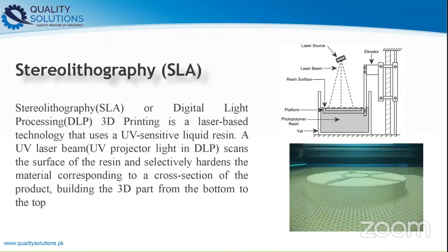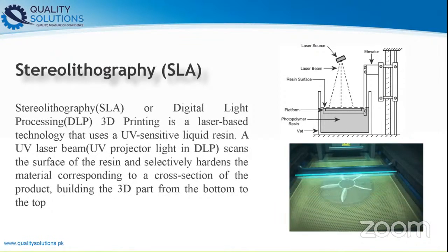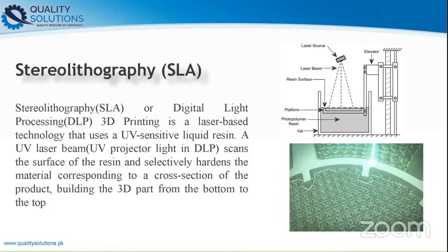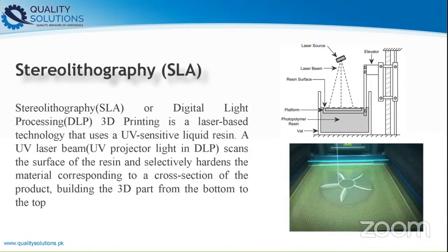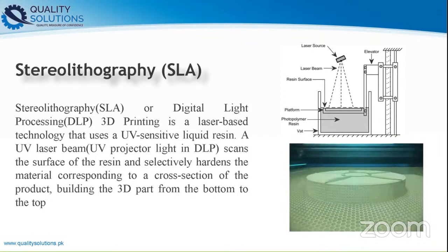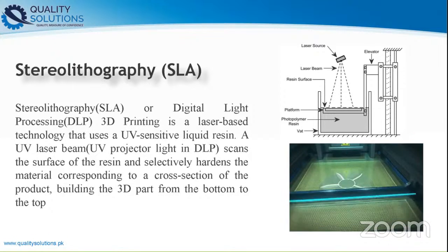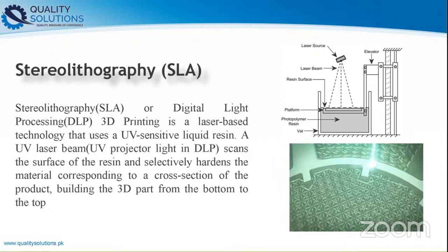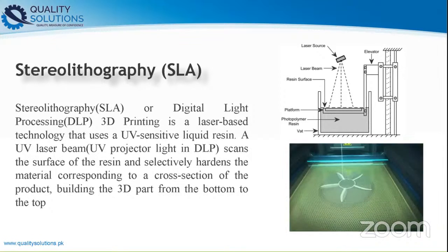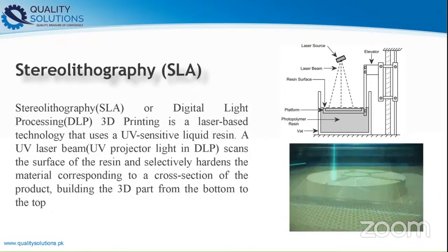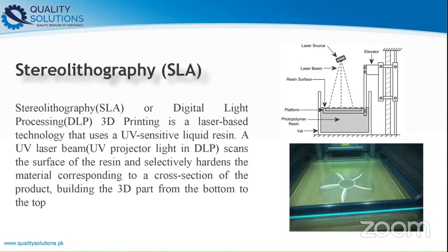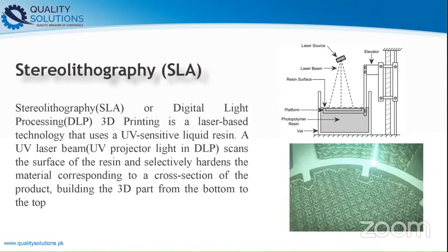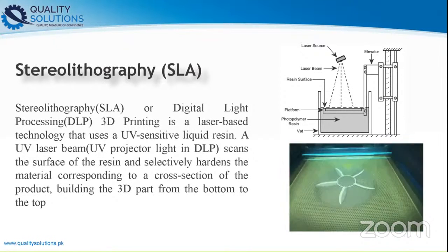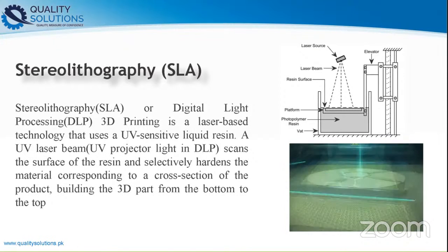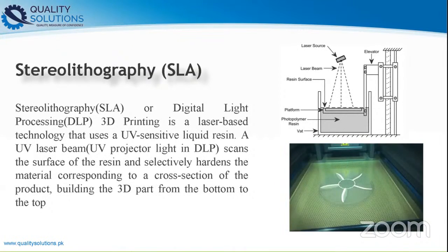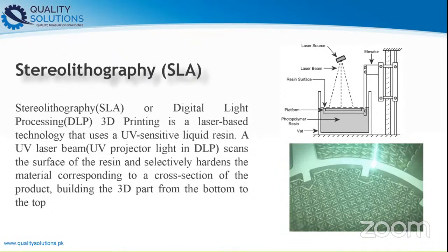Dimensional discrepancies can also occur because of the peeling process used by some SLA printers. The pulling force during the peeling process can cause the soft print to bend, which again can accumulate as each layer is built up. Resins that have higher flexural properties, meaning less stiff, are at a greater risk of warping and may not be suitable for higher accuracy applications.